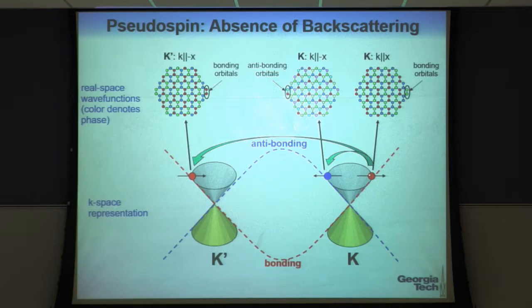Okay, so if I want to reverse the direction of current flow, let's say, so I have an electron propagating in the positive x direction. You remember that the direction that the electron goes is the group velocity. That's the slope of this cone. And so to reverse the group velocity, I go to opposite slope. That's over here. A backscattering event would have to flip the sense of bonding and anti-bonding. Now, we call the amount of bonding versus the amount of anti-bonding, we characterize that by a pseudospin. Okay, you can look at that as the pseudospin characterizing the relative phase between the wave functions on each of the sublattices A and B.